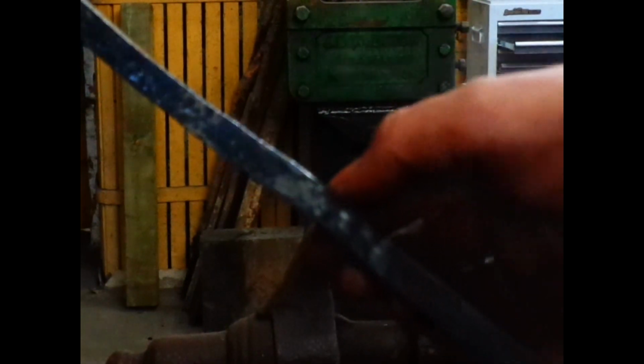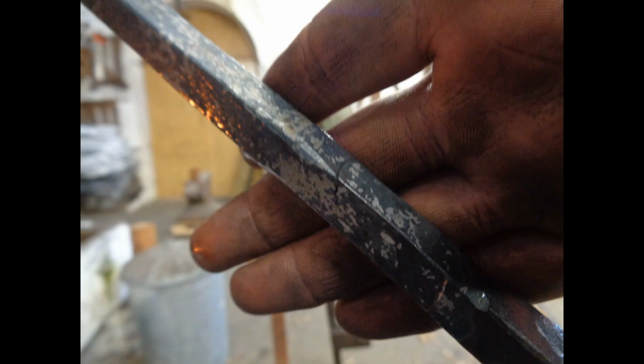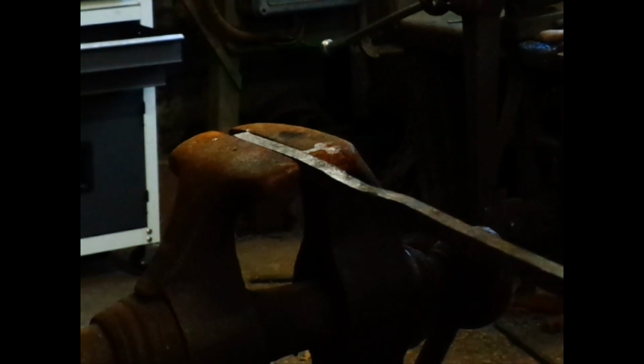After a quick clean, the flaw is evident. Even though I took a second pass off camera to try and blend it in, the damage is already done and an irreversible shearing plane had been created, evidenced by the cold shot going through the metal. Let's take a break test. This shows you why you need a long heat back from the scarf.